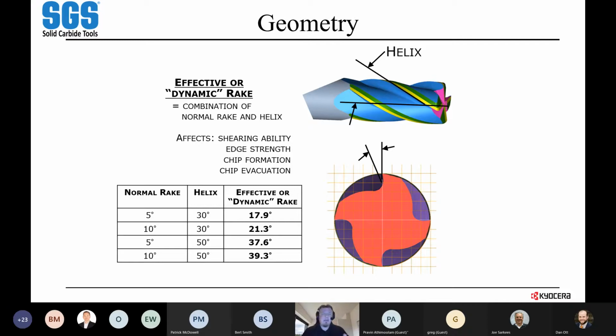On the other side of that, you can take a really high positive rake, put in a slower helix, and you can get a really good clean cutting action with a very, very rigid tool. A good example of this is our multi-carb. It's going to be basically a dedicated finishing tool, but has a really high positive rake, a really low helix angle. So with the core diameter on it, with having a really high flute count, on top of that slow helix, it's just an extremely rigid and stable tool. So we use this a lot throughout our product line in order to give that balance of best performance across multiple mediums.